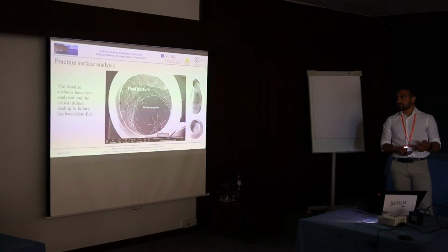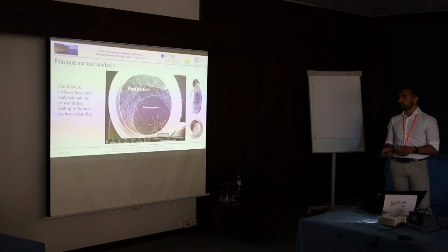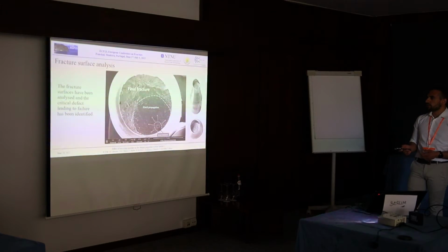Indeed, we have also performed a fracture surface analysis in order to evaluate, first of all, the phases of the fatigue failure, starting from the crack initiation, the crack propagation, and the final failure. And in this way, we were also able to identify on the fracture surface the critical defects that led to the final fracture of the specimen.